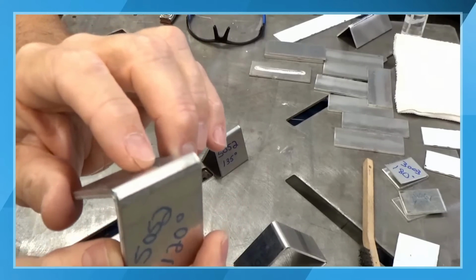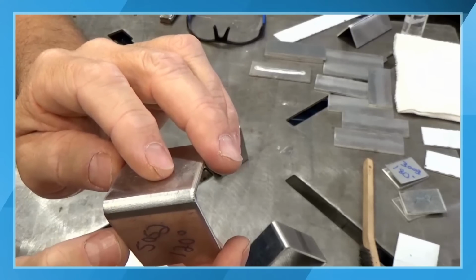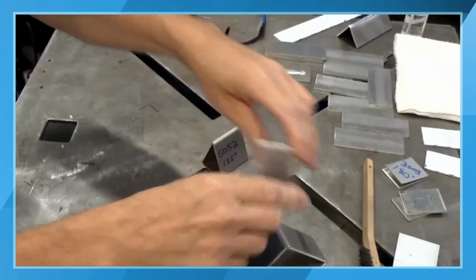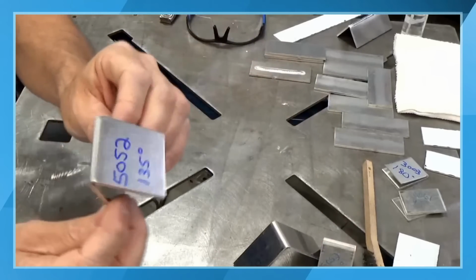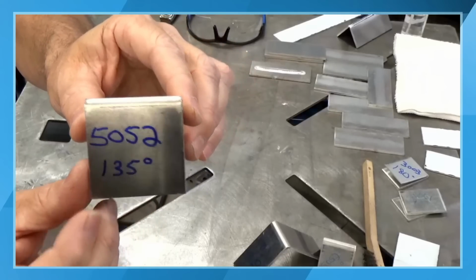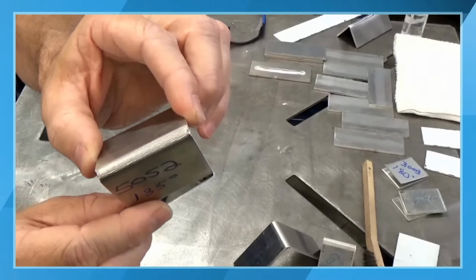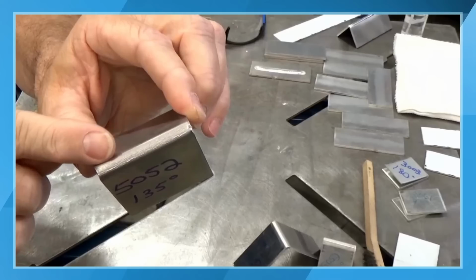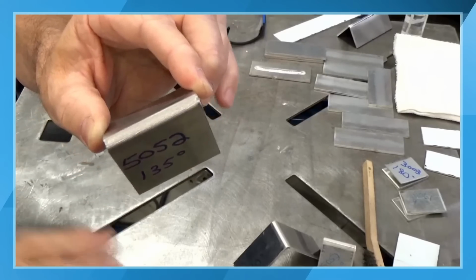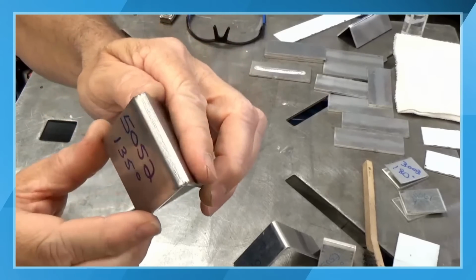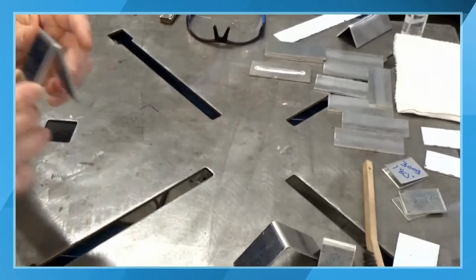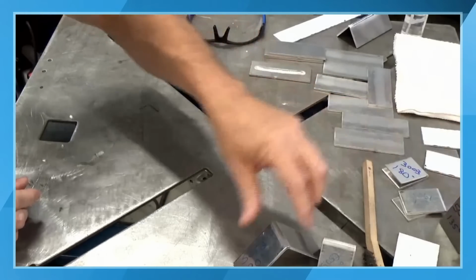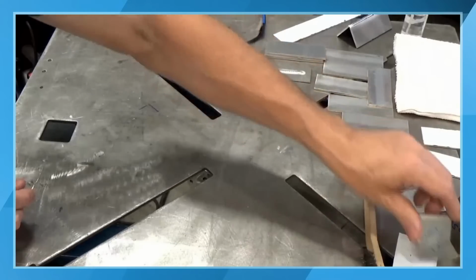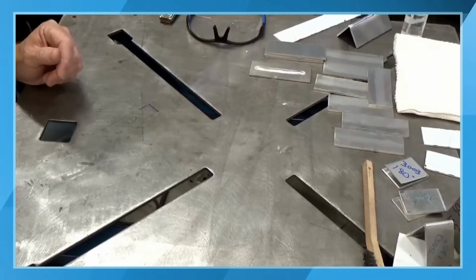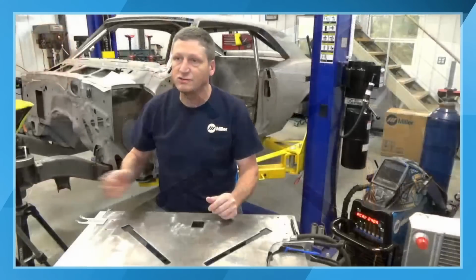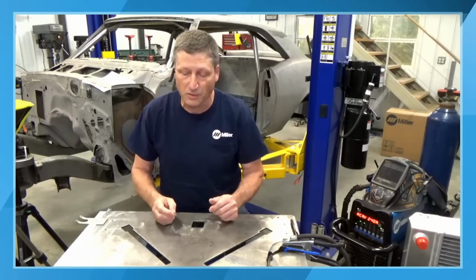Now, that micro cracking is only going to get worse. That's probably a better image of it. That micro cracking is going to get worse as you start overbending it. So this is only at 135 degrees, and you're going to start seeing that cracking being more prominent on this. So you're getting to the point now where this is going to be structurally compromised. So you may want to think about gusseting or changing that design, maybe to having that be a welded joint instead of just a purely bent or formed.